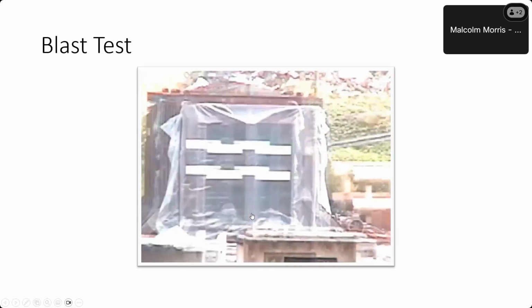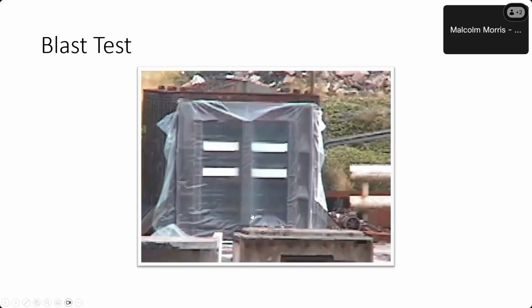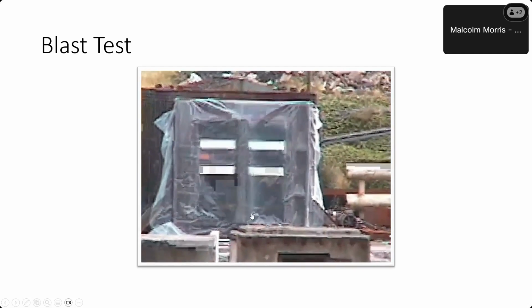You probably can't hear the sound on this one, but you get the general idea that there's a fair old force being put on that coating, and those sections will then be taken out and tested, just to make sure that the fire performance test of the coating is the same after the blast as it was before the blast. So it's quite an important test that we perform there.